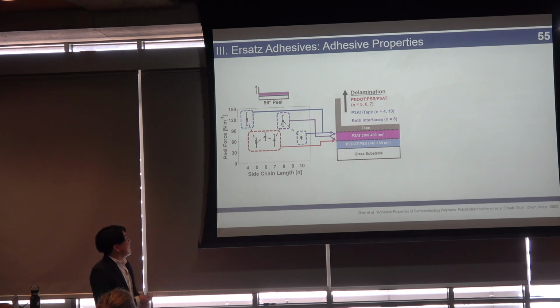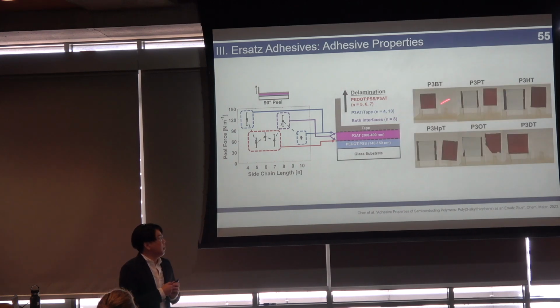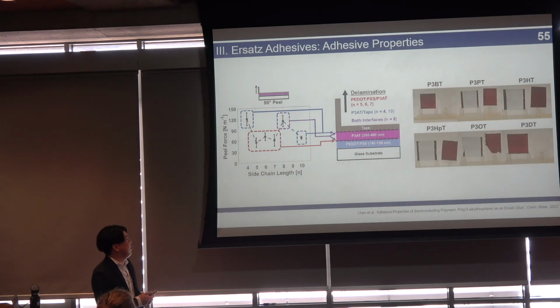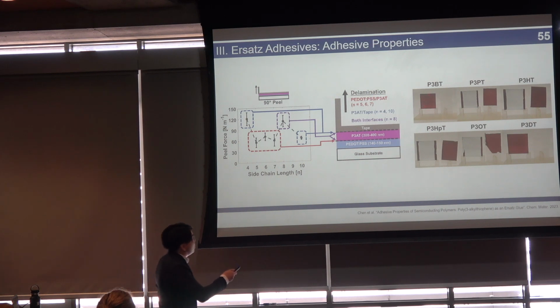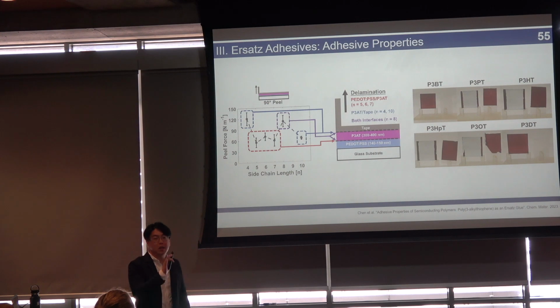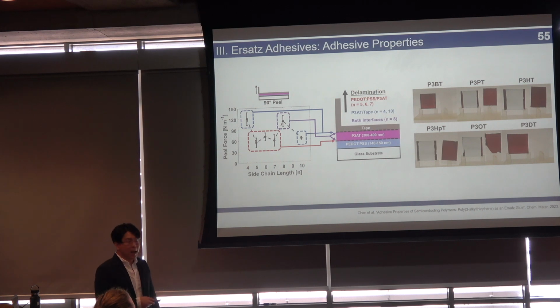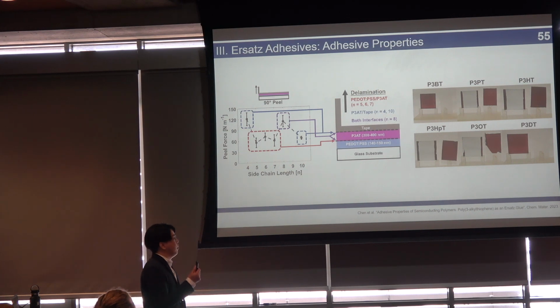layer. So what we decided to do is some more peel tests, and we put them on top of PEDOT:PSS. And interestingly, we see the debonding behavior actually changes relative to the side chain length. At P3BT, which is the shortest side chain, you get delamination between the tape and the P3AT layer. For all the other ones, you get delamination between the P3AT layer and the PEDOT:PSS layer. And then finally, for P3DT, the longest side chain, you again get delamination between the tape and the P3AT.